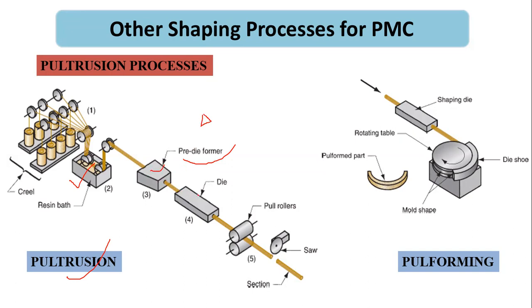And once the formation is complete, then in this die the curing occurs, mainly temperature curing, or it can be time. Then through this die the material passes, gets cured, and after curing this pulling roller pulls the whole system. There is no other system. So only these rollers pull the whole thing, and after the required size, you can cut it at any place. This is called pultrusion. A lot of fibers, these fibers can be like yarns. Sometimes you can use single fibers, or you can use yarns, whatever you want. And the compression is also done in the pre-die former. After compressing, it gets the desired shape, and that shape is continued through this die and gets cured at the same time. Any question?